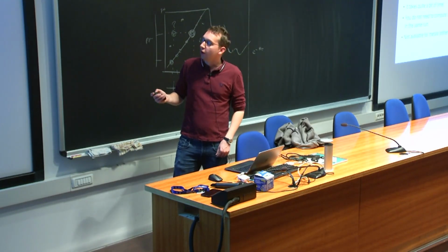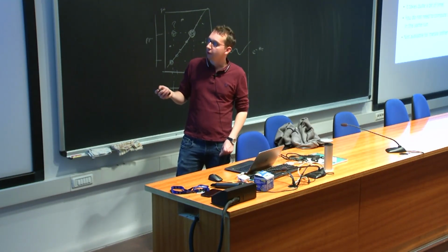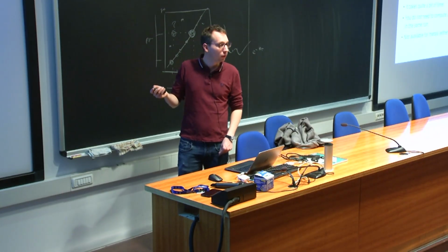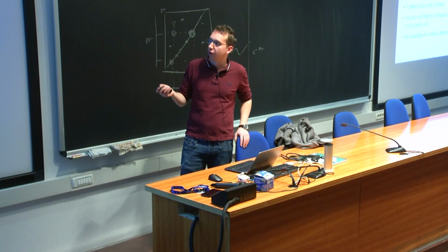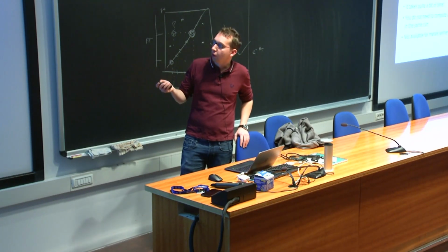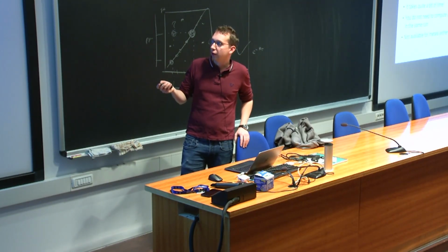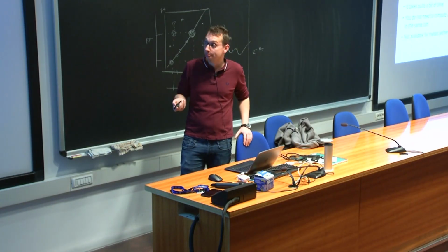So how do you ask Phonon to compute epsilon, the dielectric constant? You just set epsilon equal true in the input namelist. If true, in a q equals 0 calculation for a non-metal, the macroscopic dielectric constant of a system is computed. Do not set epsilon to true if you have a metallic system or the code will complain and stop.